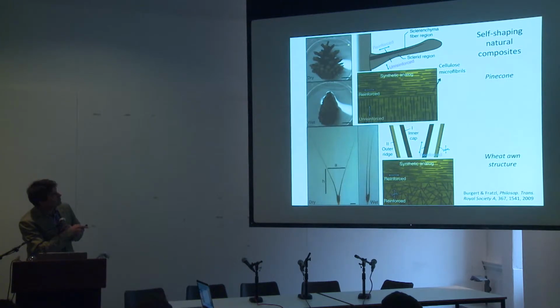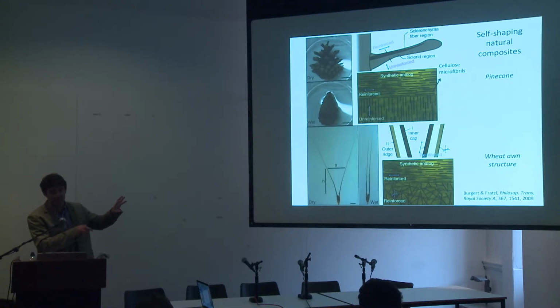If you take the pine cone, for example, in its dry state, it's open like this. If you put it in water, it closes up. Now, if you look at each one of these scales, you will be able to represent it as a bilayer, where in the top layer, cells lay down these cellulose fibrils in a horizontal fashion, in the bottom layer in a vertical fashion, so that if we swell the green matrix, which in this case is hemicellulose, there will be more swelling of the bottom layer as compared to the top layer, so the natural tendency is that the material bends, just like a metallic thermostat.